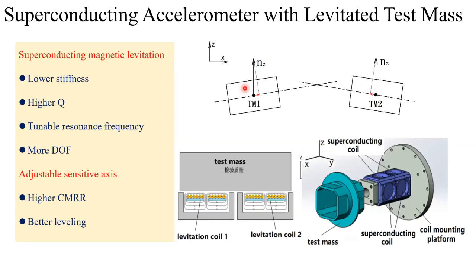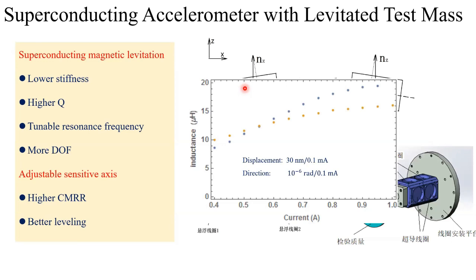I think I have talked about this, so I just skipped this slide. This is our result. In our experiment, we use a magnetic field to push part of the test mass and make it move. Our result is that once we change the current by 0.1 milliamperes, we can change the position of the test mass by 30 nanometers. This corresponds to an orientation precision of microradians. This can improve the alignment of the sensitive axis by 2 orders of magnitude compared to the detector we have now.